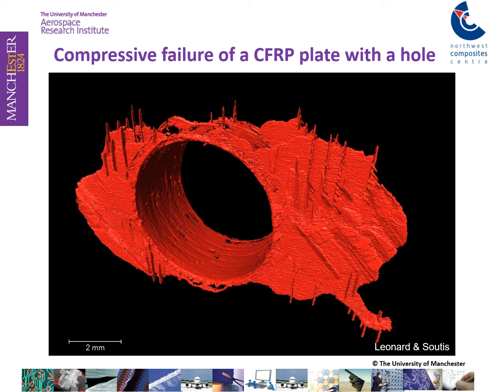And if you have a well-trained eye, then on the left-hand side at the edge of the hole, between those delaminations, you will be able to see fiber breakage in the form of fiber microbuckling, which is an instability damage mode at the fiber level.